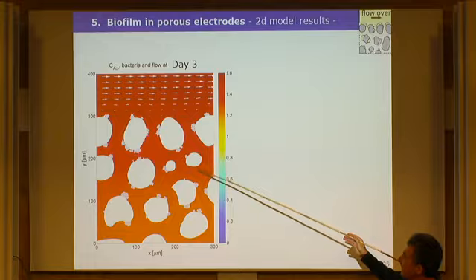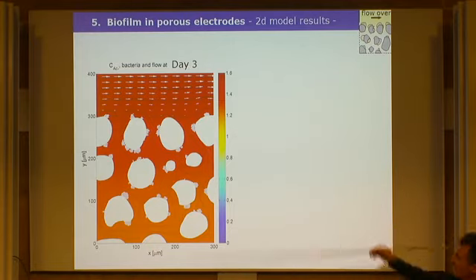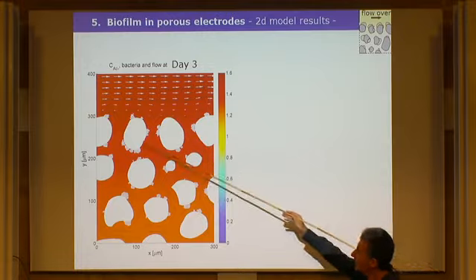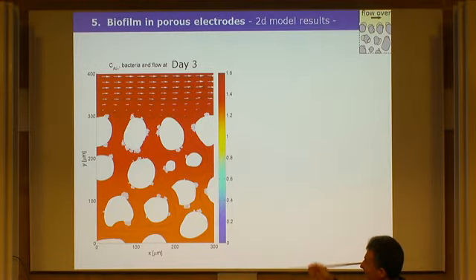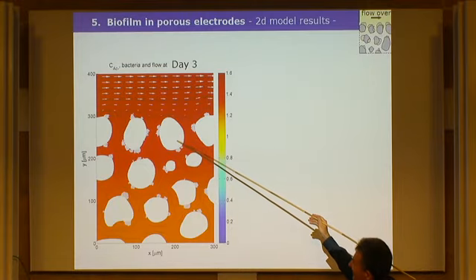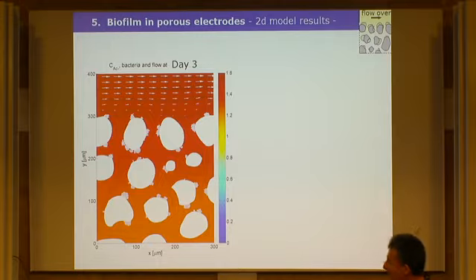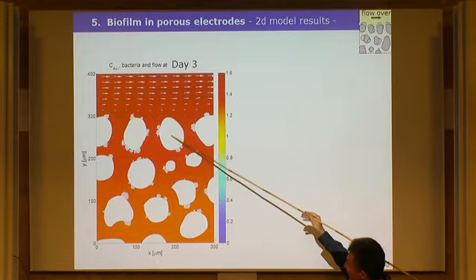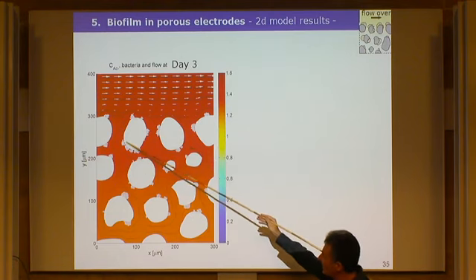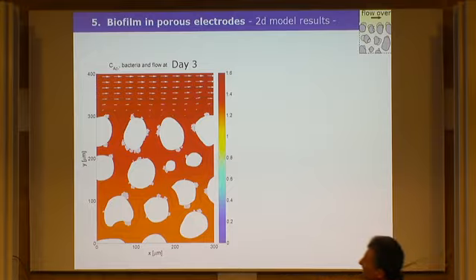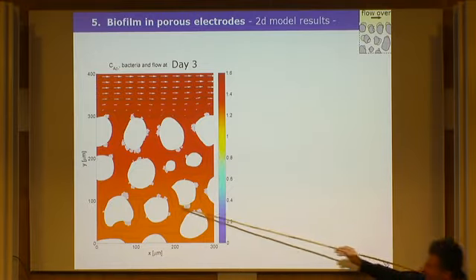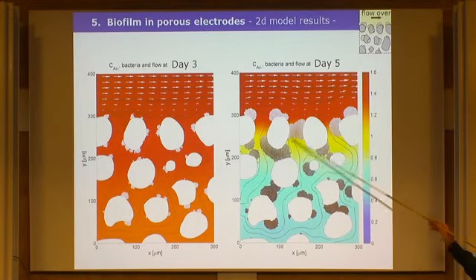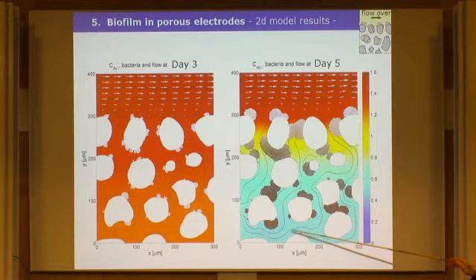So we did some simulations here. This is the acetate represented on this color scale, and these are graphite granules. Even if they are white here, you should imagine them black. That's what we do with computers. You can change colors immediately. So these are graphite granules, and these are colonies growing on the granules. At day 3, there are a few colonies now formed. There is no acetate limitation, but if you look after 5 days, these colonies blocked somehow the porous medium, and there is little acetate left here, deep in the biofilm.